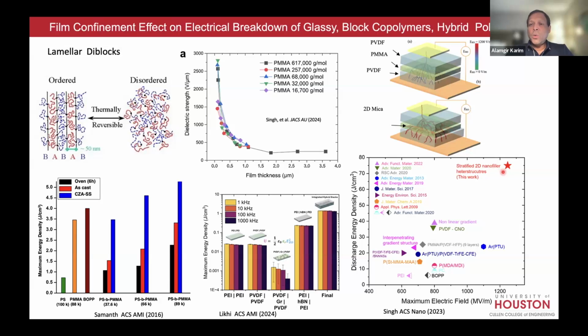And by the way, there's a lot of work that's been done where people have looked at polymer nanocomposites where they put silica particles, spherical particles, polymer-grafted silica particles, but all spherical or even rod-like geometry, and they don't get anywhere close to this. In fact, the dielectric constant will go up because you're adding an inorganic, but the breakdown voltage actually goes down with these spherical and rod-like particles.